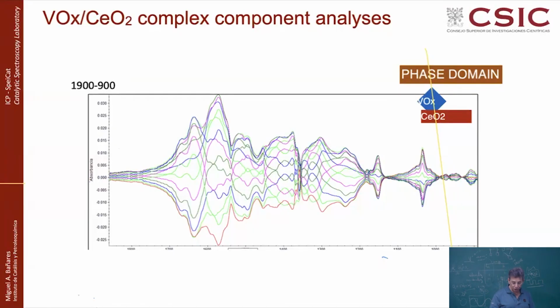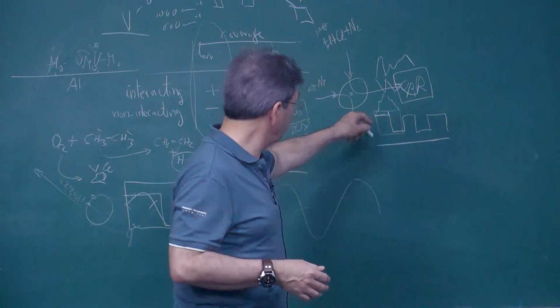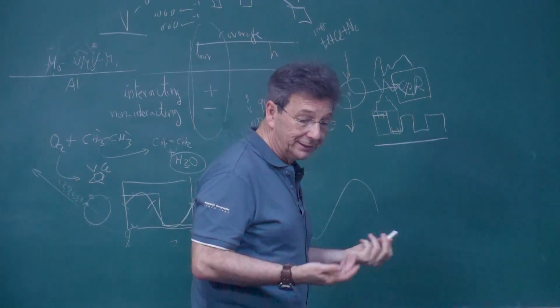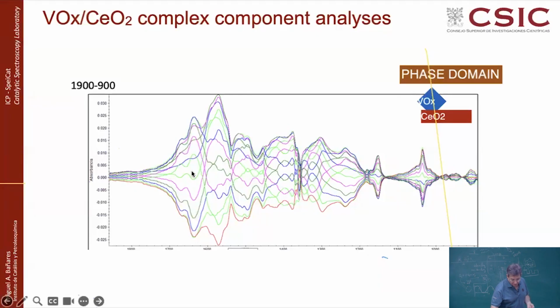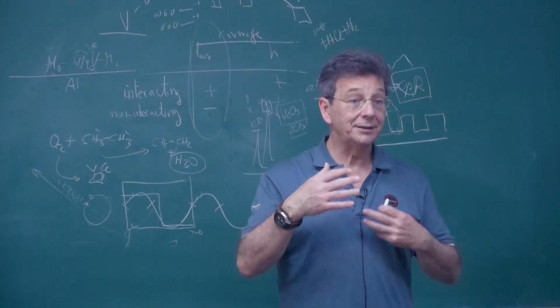And this is basically what you see here. A little bit of a chaos with a lot of bands going up and down. But you also see this at a few representative moments of the phase, like here, here, here, because that can be almost continuous. But what you see is that sometimes these two bands grow, and more or less these two bands grow at the same time. And later on you get this band that is growing, but independent of that one. So even if you look here, you can say that these two bands belong to one species, and that belongs to another species, which are actually evolving at different moments.